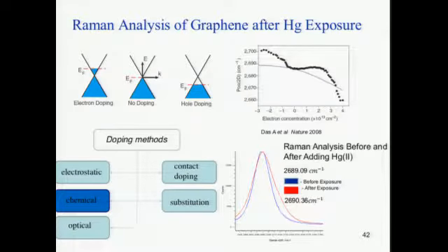I will say this is a sample that was created by CVD and transferred to a silicon oxide layer. But nevertheless, this is showing before exposure to, in this case, mercury, that afterwards we have a shift in the wave number to an actual higher wave number. And according to some theoretical studies, that's indicative of p-doping